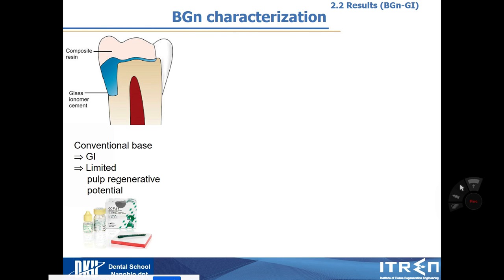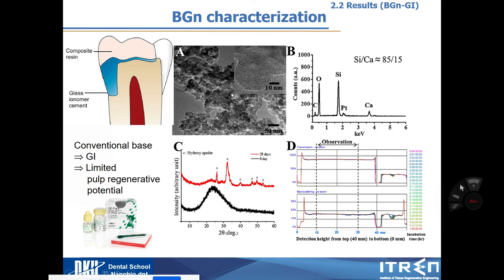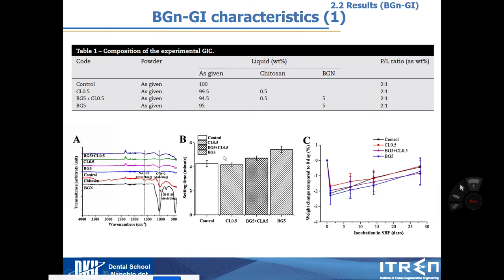And then, secondly, glass ionomer is originally used as a base or dentin restorative material. But they have very limited regenerative potential. So I want to increase it more using bioactive glass. After incorporating the bioglass, I check that bioglass is successfully loaded in this glass ionomer, and setting time is a little bit increased, but it's not much difference. And then weight change is almost similar.